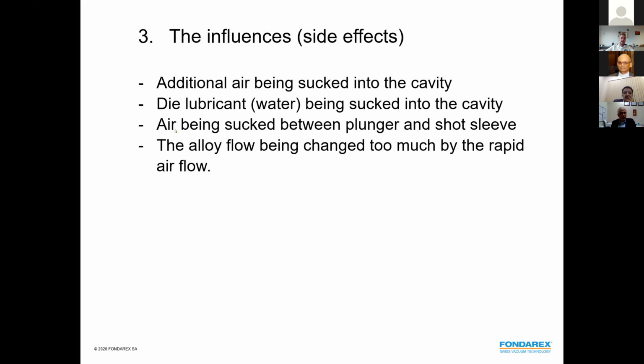Then another big problem is air being sucked in between plunger and shot sleeve. We have to start the vacuum somewhere after the plunger overtakes the pour hole, and often the plungers are not tight enough, and there's always some influence that some air comes in there as well. And then of course the turnover of oxygen is higher, and instead of having better castings with vacuum, some people say, well, I tried vacuum, but I didn't get any better parts. Why? Because we took out some air, but some other air came in, and at the very end, we had a higher turnover of oxygen, and the parts were not any better than without vacuum.